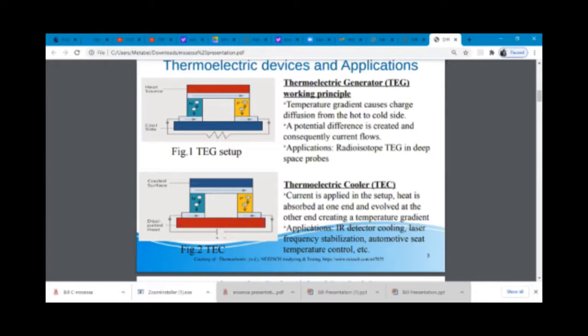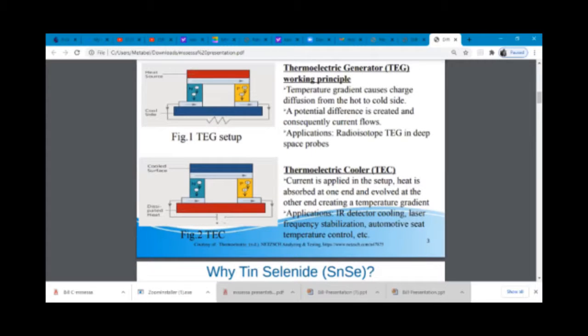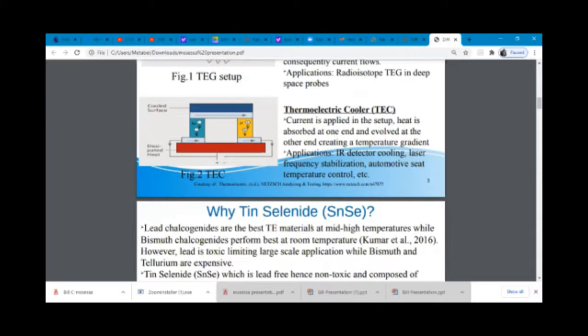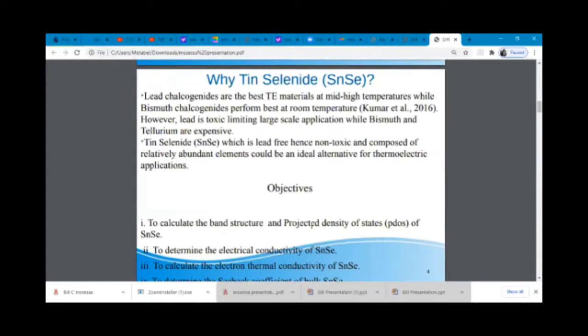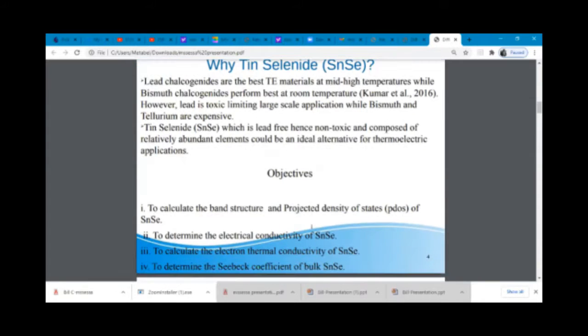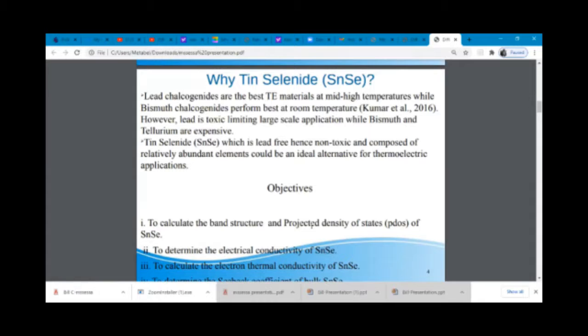So why tin selenide? As has been mentioned by other presenters, lead is toxic. We find that lead chalcogenides, for example lead telluride, are the best thermoelectric materials at high temperatures, while bismuth chalcogenides like bismuth selenide and bismuth telluride perform best at room temperature. However, due to lead being toxic, it's a major environmental concern, and also bismuth and tellurium are expensive, so these limit large-scale applications of these devices.